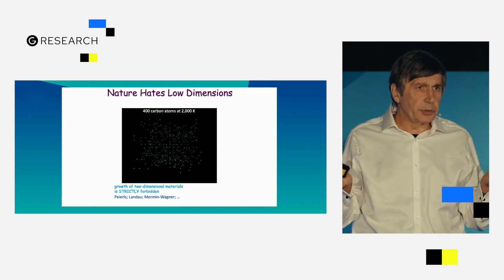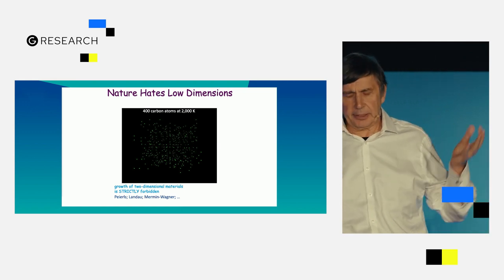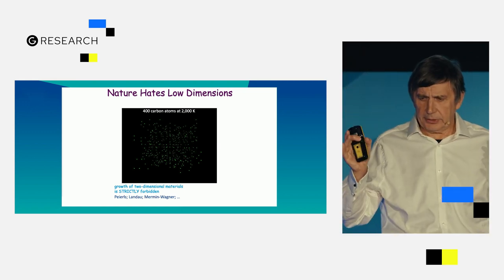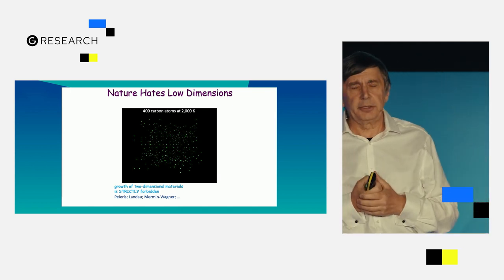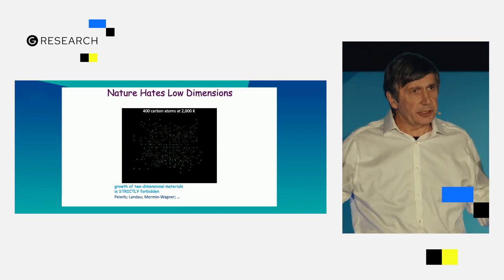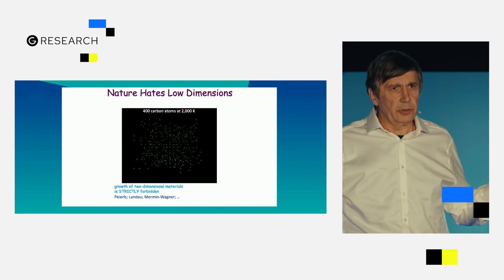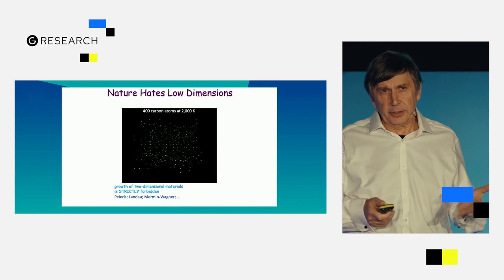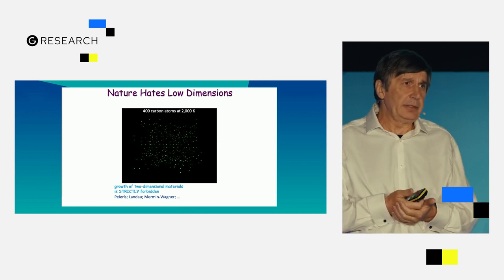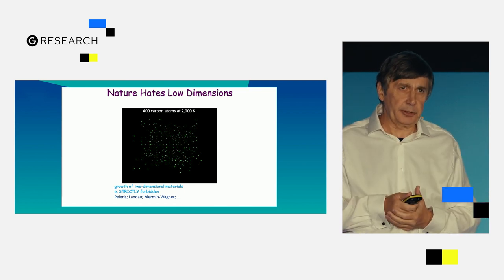Essentially growth of low dimensional materials is forbidden in our three dimensional world. And for this there is a hundred years history coming from Peierls, Landau, Mermin Wagner, Kosterlitz Thouless and so on. Essentially vibrations are so violent in low dimensional space for one and two dimensional objects that they destroy this order. And only order possible in three dimensions. So you wouldn't find low dimensional objects for this simple reason unless they are very small.